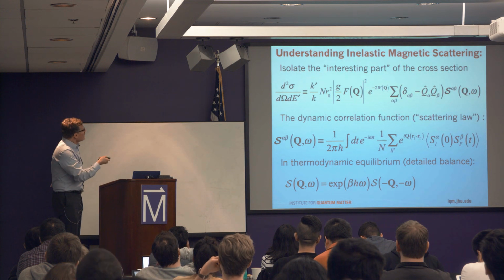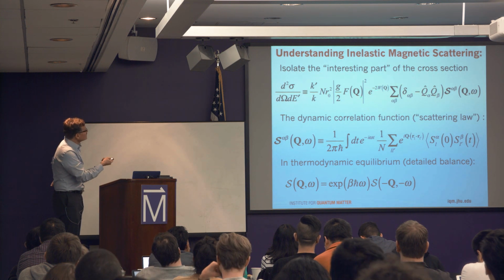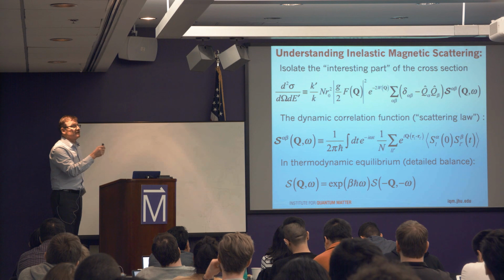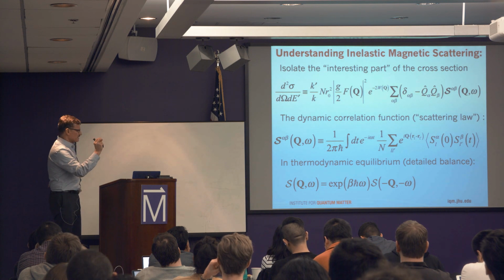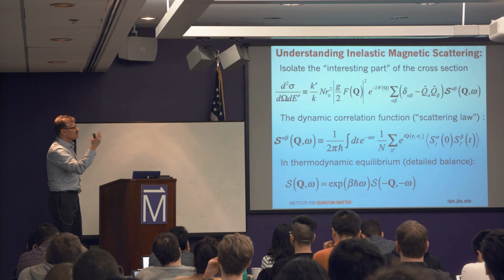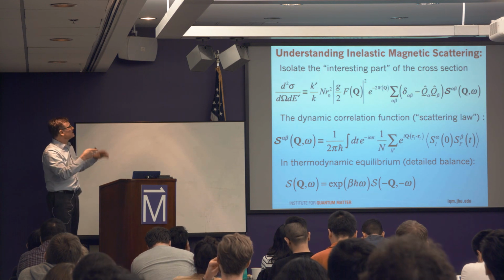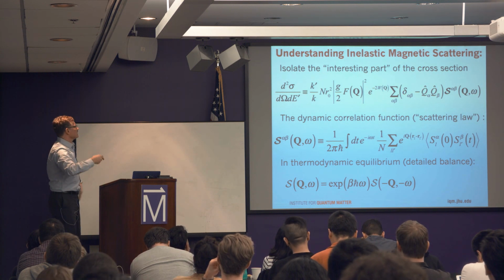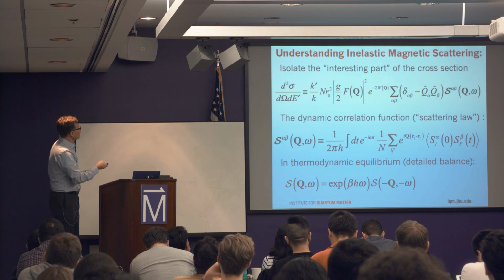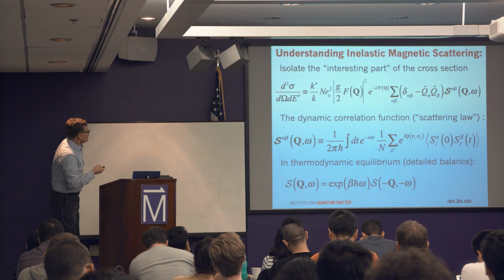And then you have here the so-called Debye-Waller factor, having to do with the fact that the whole atom is moving about due to thermal or quantum lattice vibrations, and that will also wash out the cross-section at larger wave vector transfer. And this is the overall scale for the magnetic scattering that we mentioned previously.